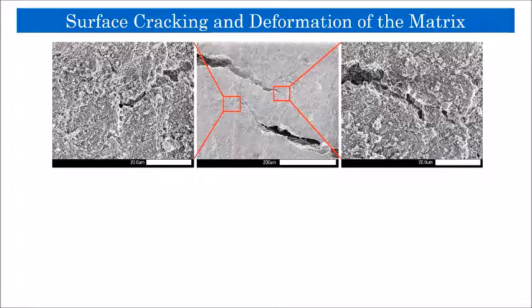Pre-shock and post-shock SEM studies on samples showed that the samples made of matrix material only are more susceptible to thermal shock compared to reinforced composites as expected. In this figure, you see matrix surface cracking due to thermal shock.